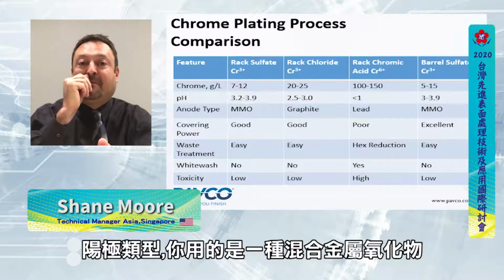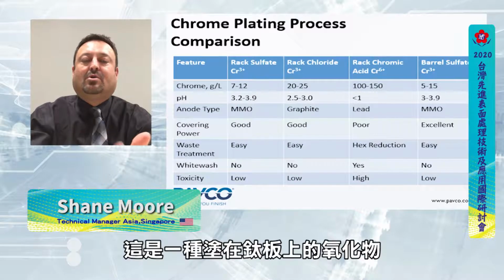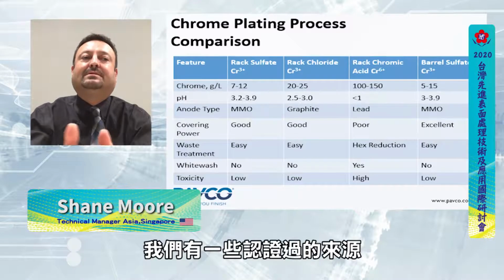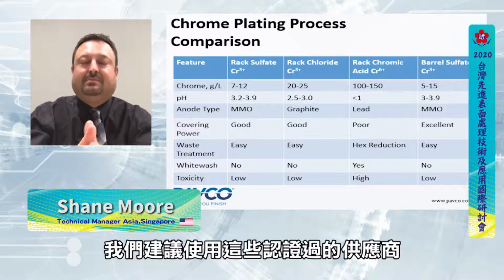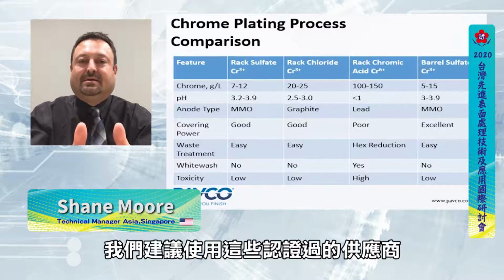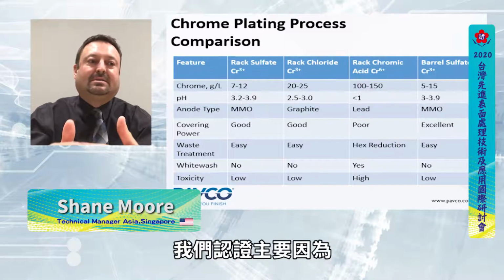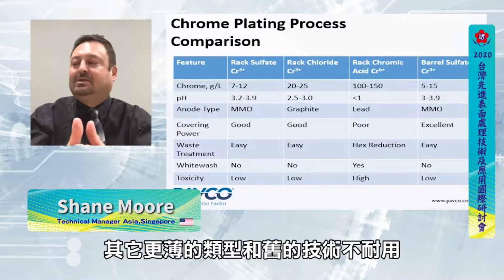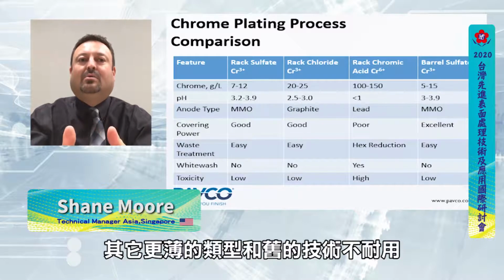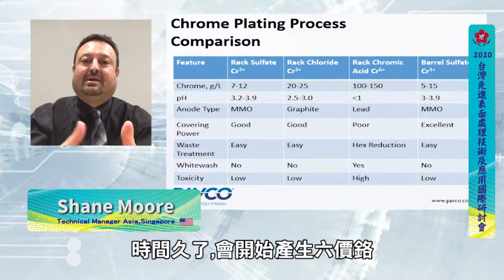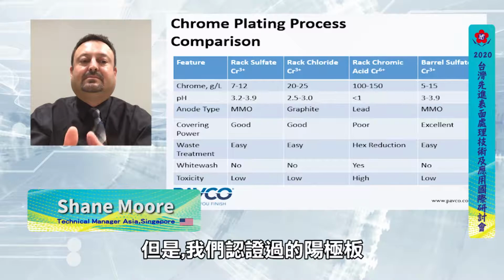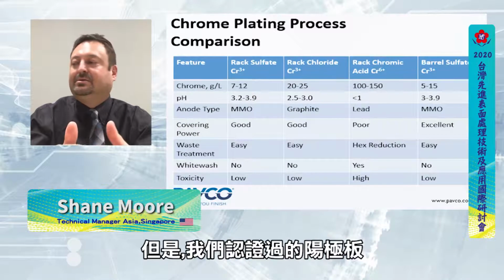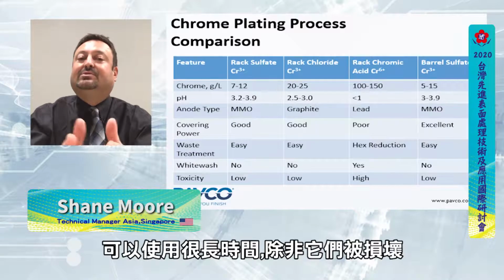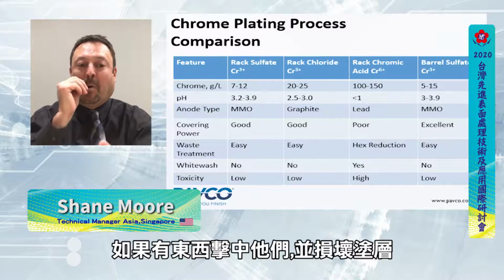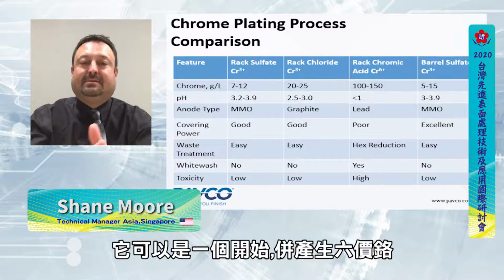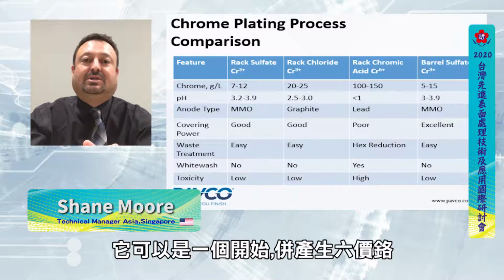The anode type you have to have is called a mixed metal oxide. It's a coating that goes over titanium, and we have some approved sources. We really highly recommend that we use these suppliers that we have approved, just because the thinner type and the older technology MMO coated anodes would not last very long, and they would start generating hexavalent chromium. But the sources that we have identified as having the best anodes last a very long time, unless they're damaged. If something hits them or damages the coating, then it can be an initiation site to start generating hex chrome.